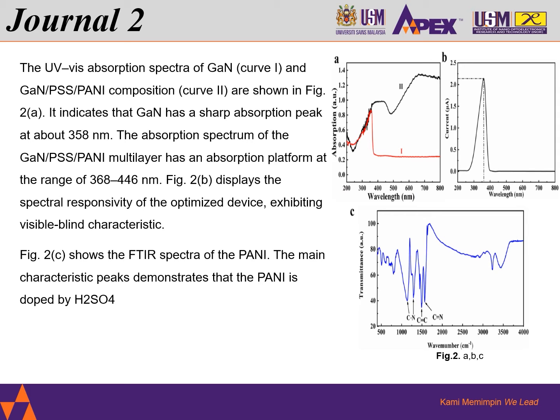The UV-visible absorption spectra of GaN curve 1 and GaN-PSS-PANI composition curve 2 are shown in figure 2a. It indicates that GaN has a sharp absorption peak at about 358 nanometer. The absorption spectrum of the GaN-PSS-PANI multilayer has an absorption platform in the range of 368 to 446 nanometer. And figure 2b displays the spectral responsivity of the optimized device, exhibiting visible blind characteristic.